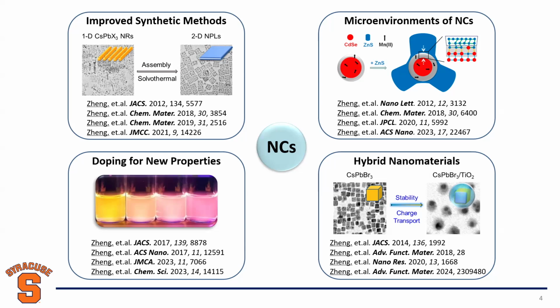In addition to size and shape, we want to understand microenvironments, for example, surface states and interfaces, right? This is a very interesting area. We developed a very sensitive optical probe to allow us to tell the difference between the surface atoms and the atoms in the interior, in the core of nanocrystals, and even the interface for some core-shell structured nanoparticles.